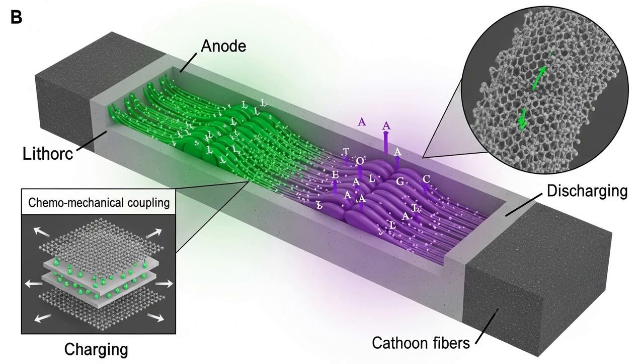But here's where it gets really complex. There's a phenomenon called chemomechanical coupling. When you charge the battery, lithium ions go into the carbon fibers, causing them to swell slightly. When you discharge it, the ions leave, and the fibers shrink. This constant swelling and shrinking creates internal stress in the material. If it's not managed properly, it can cause micro damage and degrade both the strength and the battery capacity over time.